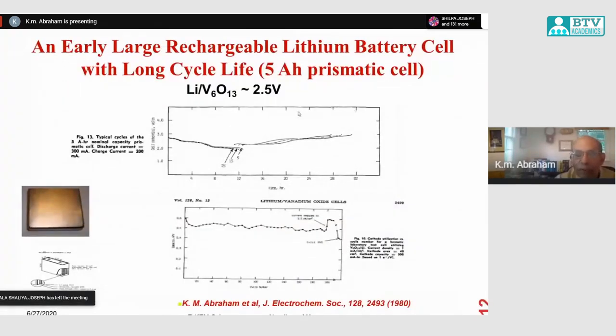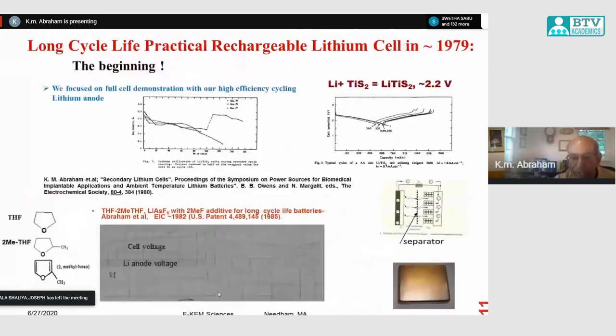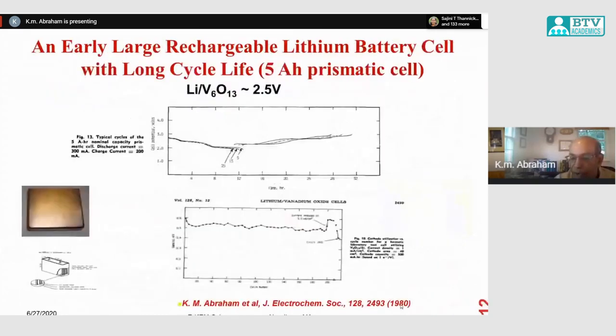So following that, we published these things. This was first published at an Electrochemical Society meeting in 1980. Then subsequently we published other papers. In this case we used a vanadium oxide cathode material. As I said, most people were working on cathode material. There were several cathode materials available, but the anode was the problem. So we made a significant improvement to that, and we were able to make other rechargeable lithium metal anode batteries.